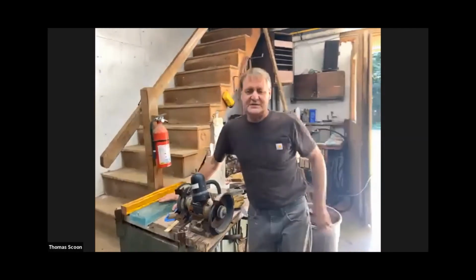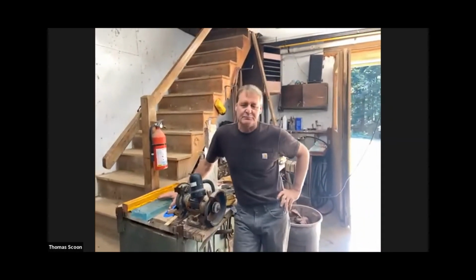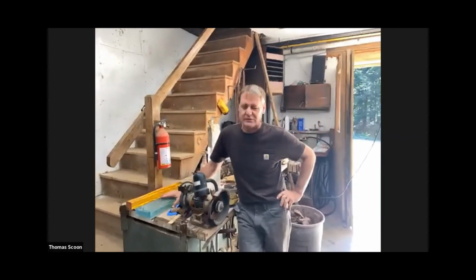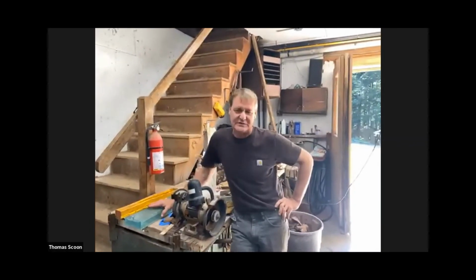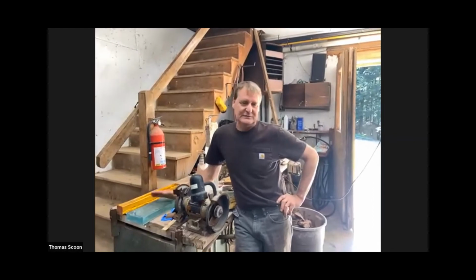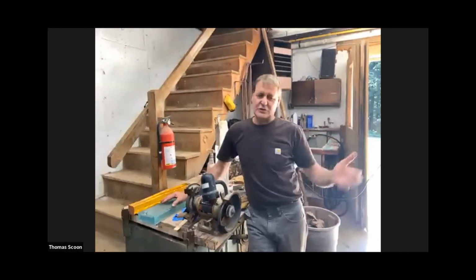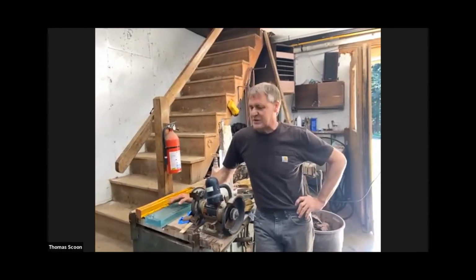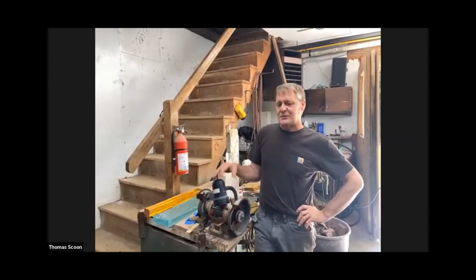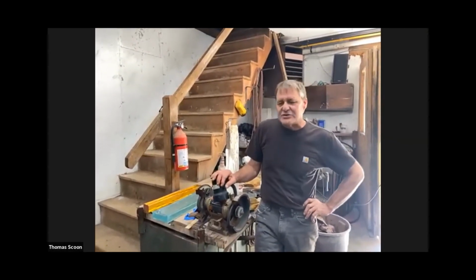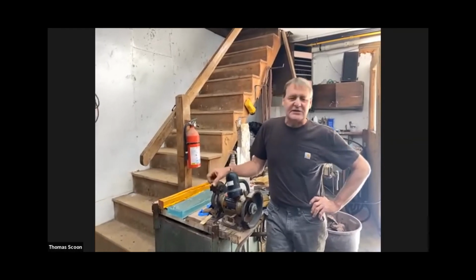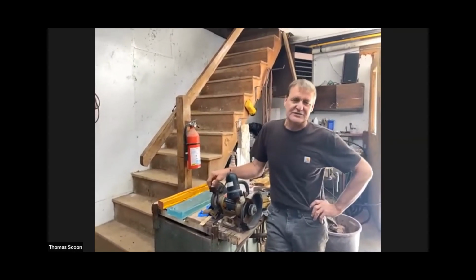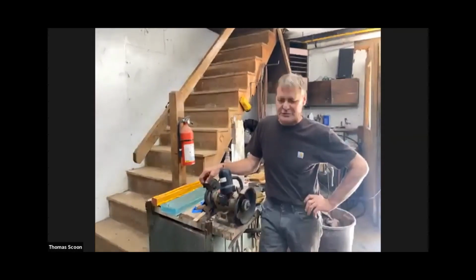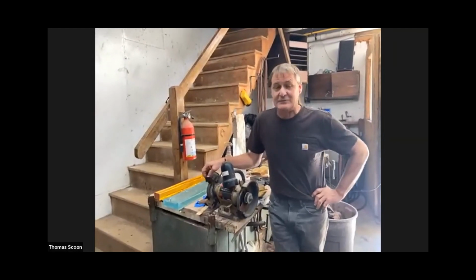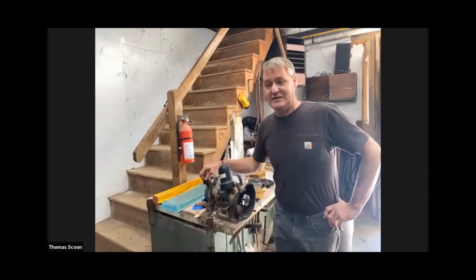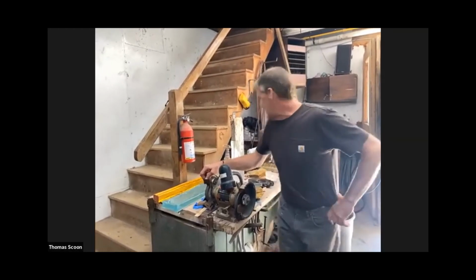Large scale pieces can weigh up to 100 pounds plus. So the glass is close to $2,000 on a large scale piece. Mold material, wax, and electric bills are substantial, especially when you're annealing pieces for 3 or 4 weeks. And then the bigger issue is that when you're casting glass, there's no guarantee that it's going to come out. So there can be a number of issues. I've been doing it for now 25, 30 years, and it's just the nature of the beast.